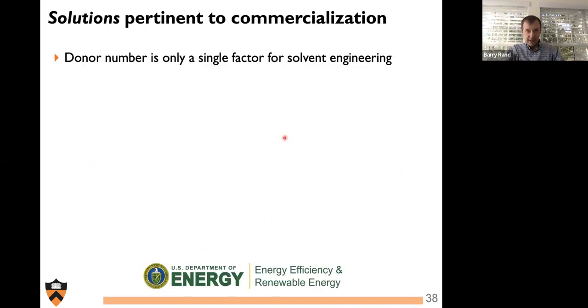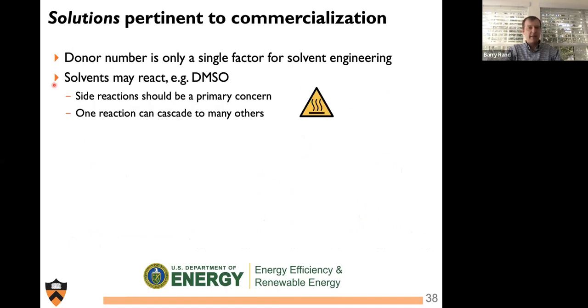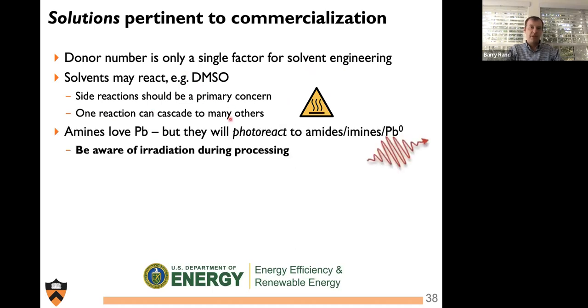So now to return to the pun, the solutions for Perovskite commercialization. Donor number is only a single factor when considering solvent engineering. One should also consider that solvents may react, and I think I've given certain cause to be concerned and alarmed about DMSO. Side reactions should be a primary concern, especially in the presence of DMSO and heat. And it also should be stressed that one reaction can cascade others. That is in fact what happens in the case of making MFA, which requires that initial proton transfer step with DMSO, which may have been expected, but the other one was certainly more of a surprise.